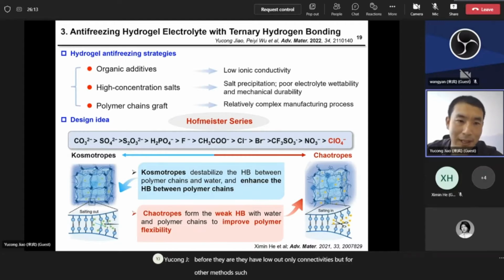For other methods, such as the highly concentrated salts, the issue is they have salt precipitation and poor electrolyte wettability, and when they are used in the hydrogels, they will damage the mechanical strength of the hydrogels. And another effective strategy is to graft polymer chains. Professor Zhi has already done a lot of excellent work in this field. But for some of the literature, the method is relatively complex and may not be suitable for future commercial application. So here we still need to find a more facile strategy to get a high performance anti-freezing hydrogel electrolyte.